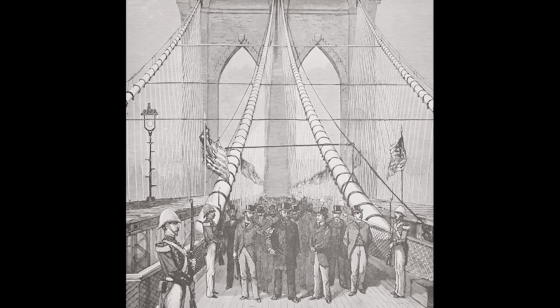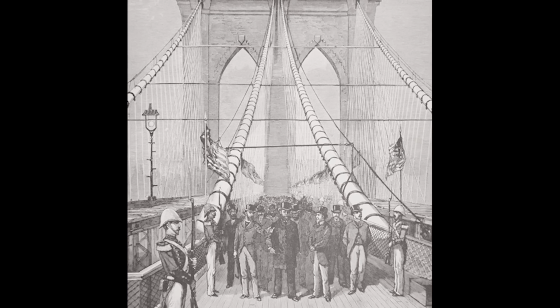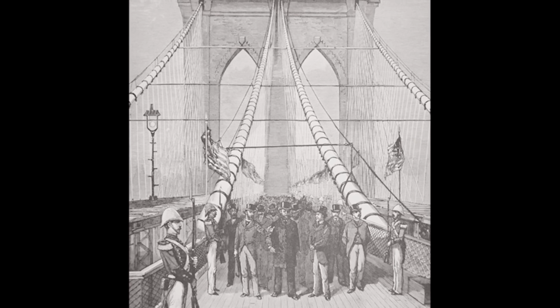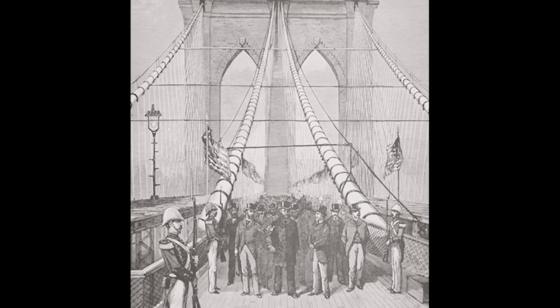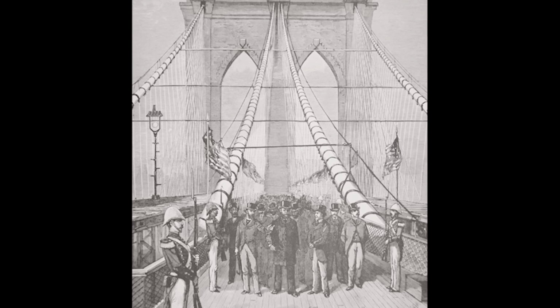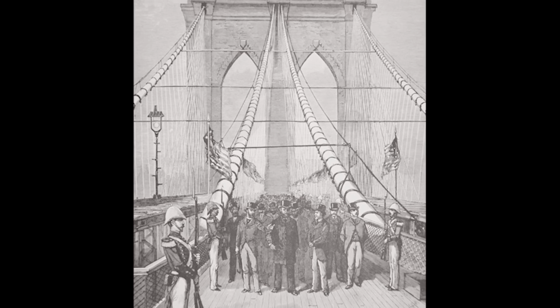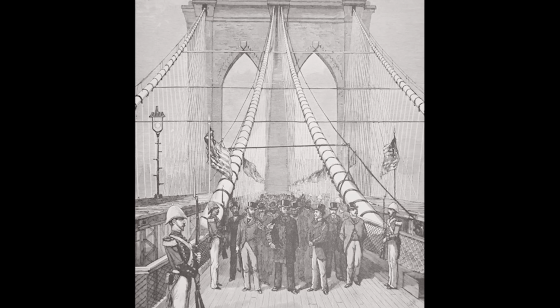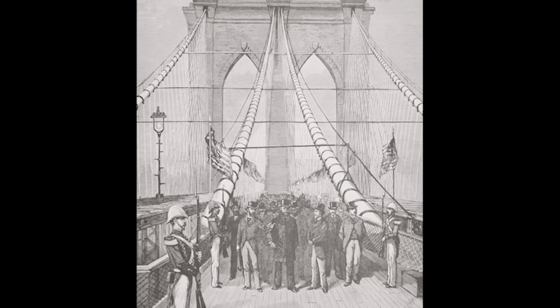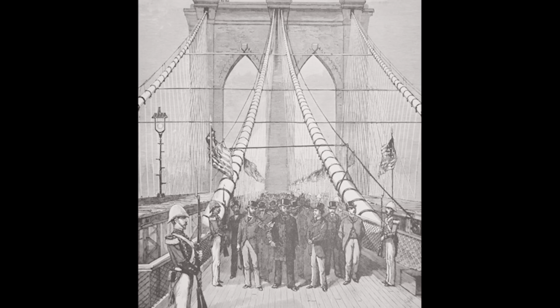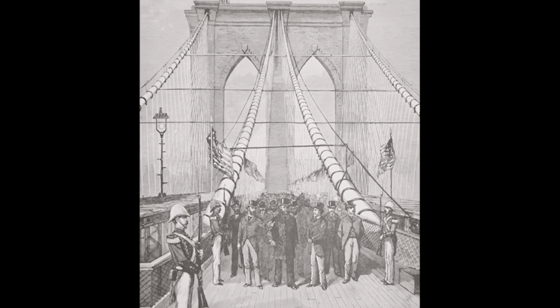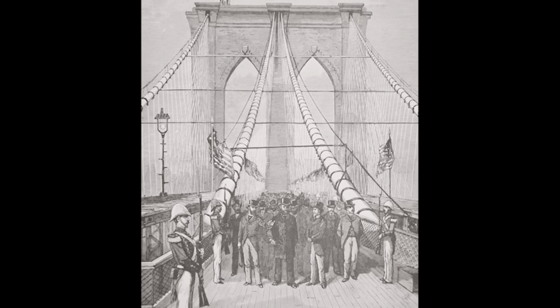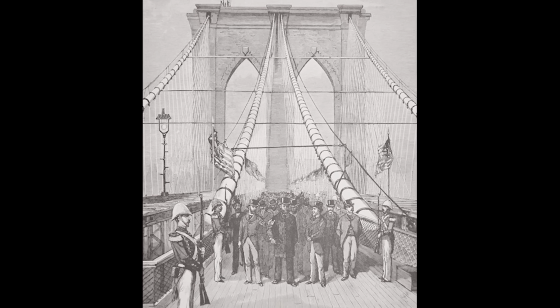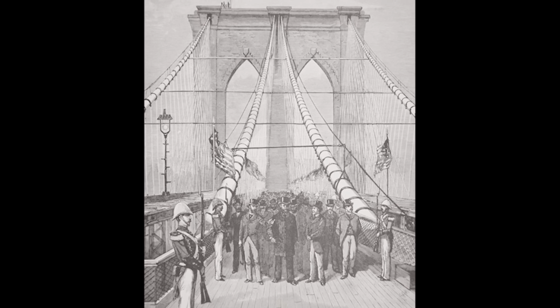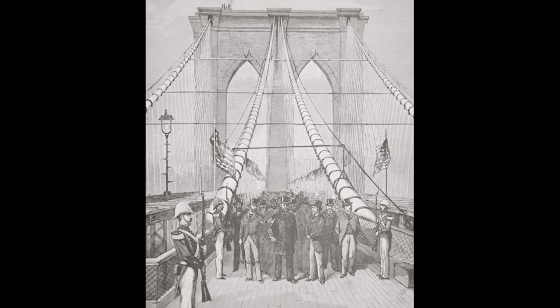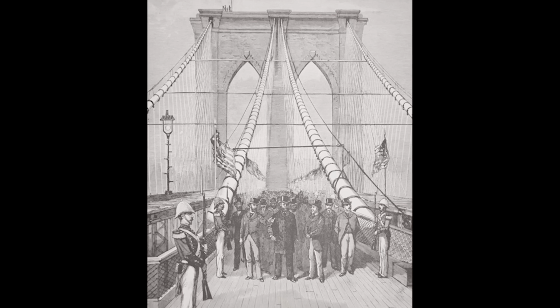The economic mathematics favored heavy initial protection over repeated maintenance cycles. Modern systems that prioritized low initial costs through thin coatings and minimal sealing often required major rehabilitation within 25 years, consuming resources that exceeded the additional expense of thicker protection applied during original construction. The Brooklyn Bridge cables had avoided this cycle through specifications that treated protection as investment rather than expense.